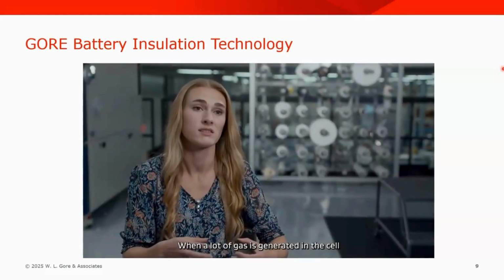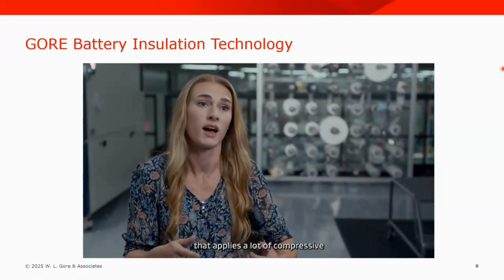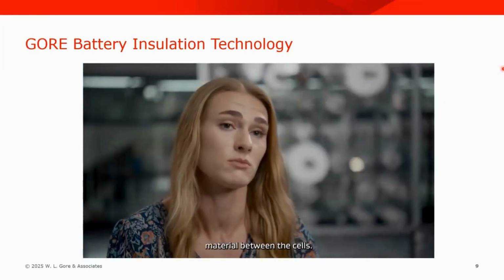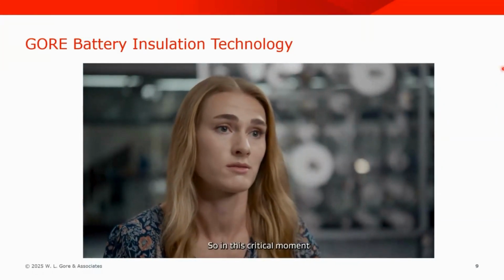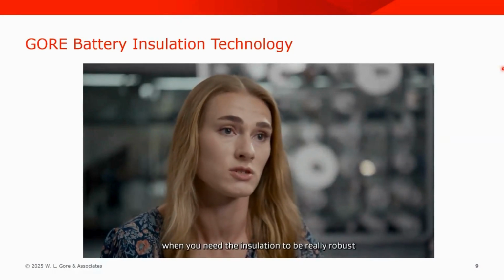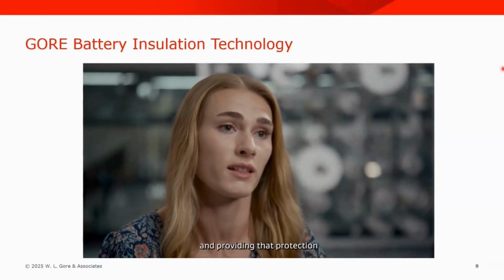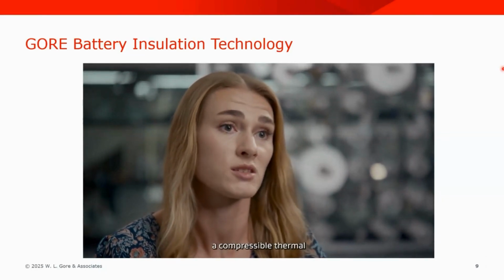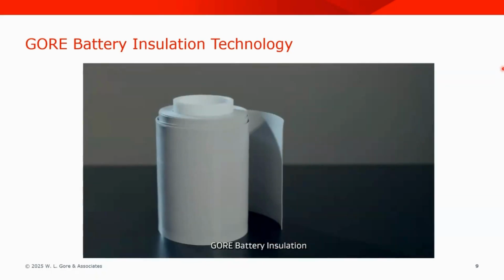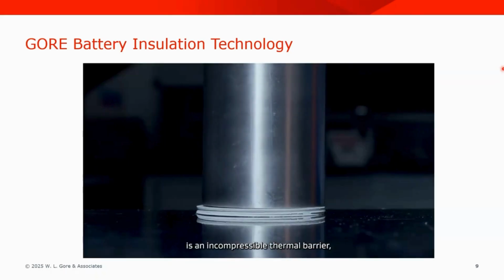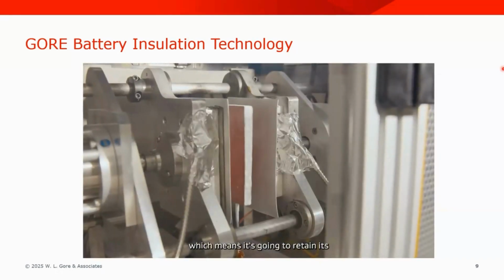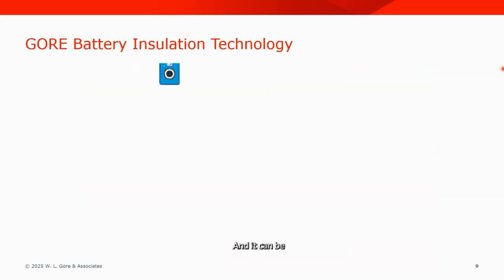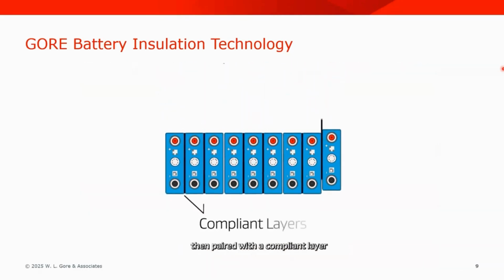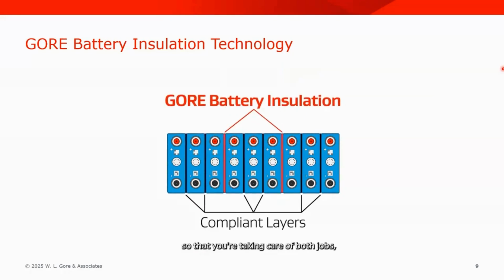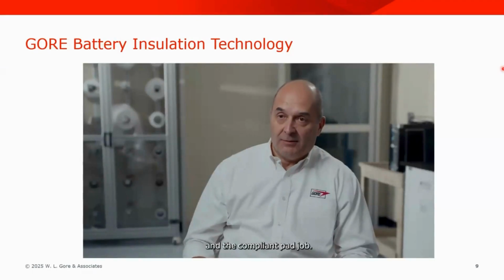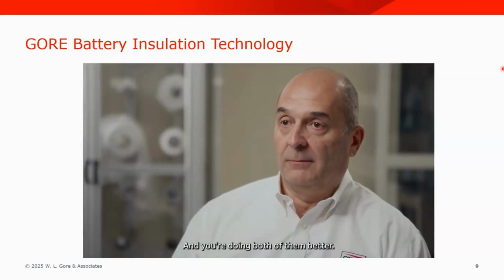When a lot of gas is generated in the cell, that applies a lot of compressive stress on the insulation material between the cells. So in this critical moment when you need the insulation to be really robust and providing that protection against thermal propagation, a compressible thermal barrier will be compromised. GORE battery insulation is an incompressible thermal barrier, which means it's going to retain its thermal properties even under compression. And it can be then paired with a compliant layer in alternate cells so that you're taking care of both jobs, the thermal barrier job and the compliant pad job, and you're doing both of them better.